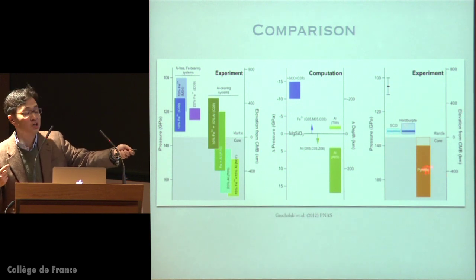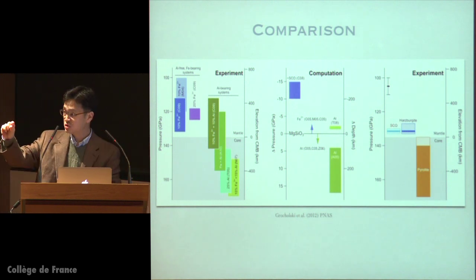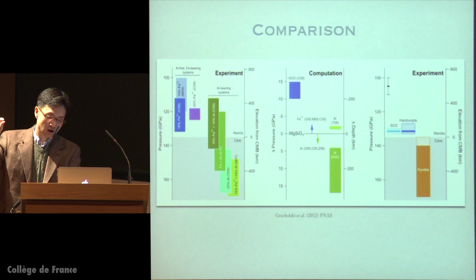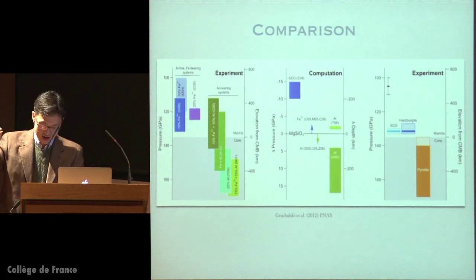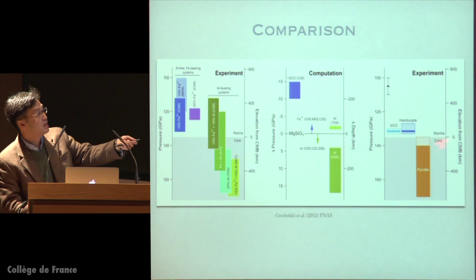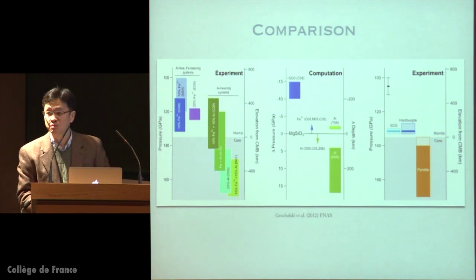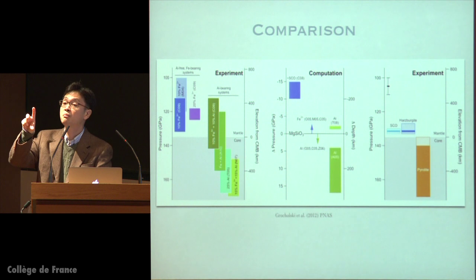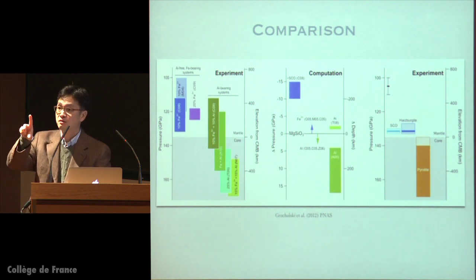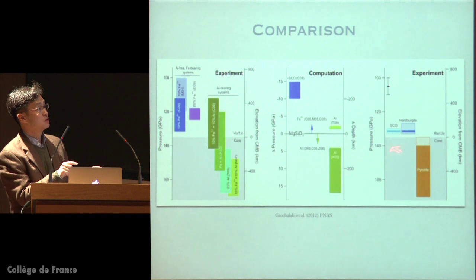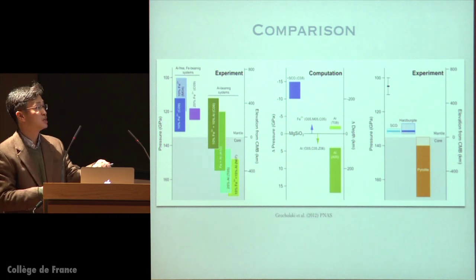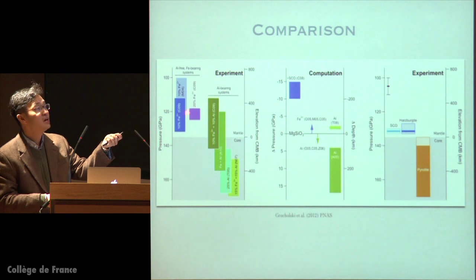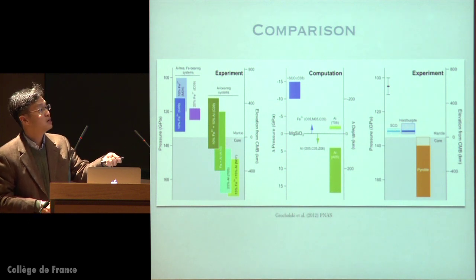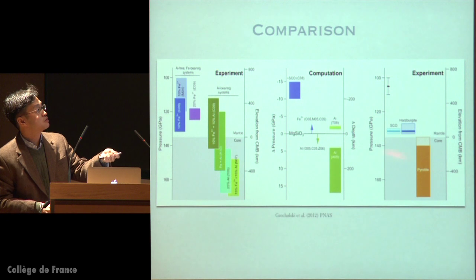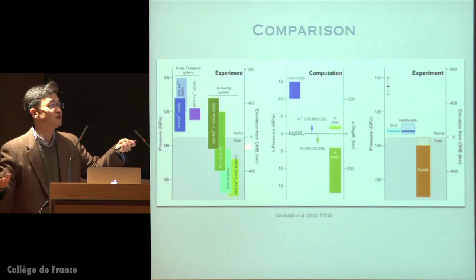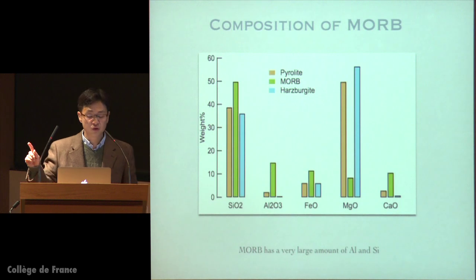The convention here is that the dark area represents the lower bound of the thickness, and including the dark and bright area, it shows the upper bound. So it gives you an error bar of our estimate for the thickness. You can see that the San Carlos olivine decreases the thickness a lot with respect to the iron-bearing system. That's clearly an effect from ferropericlase. And for the pyrolite, you are influenced mostly by the deepening effect and thickening effect of aluminum, even if you have ferropericlase.